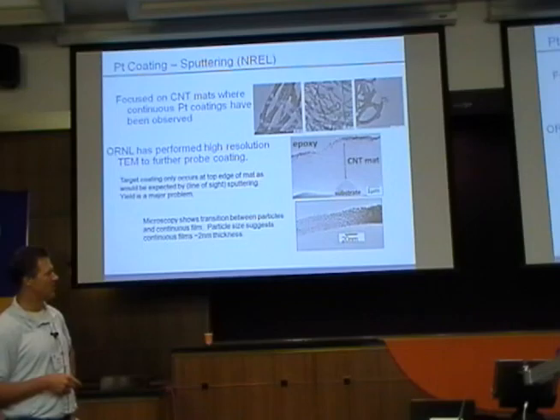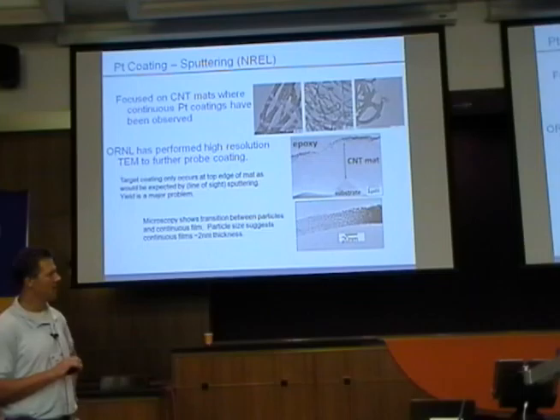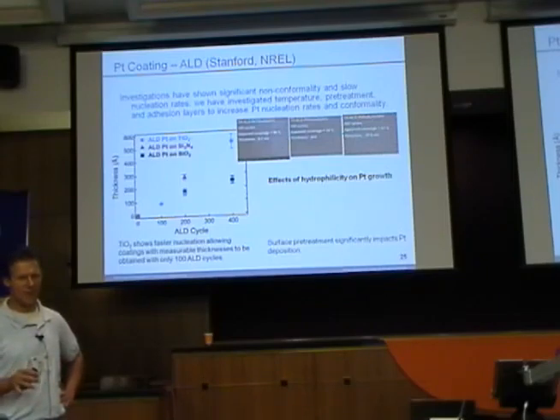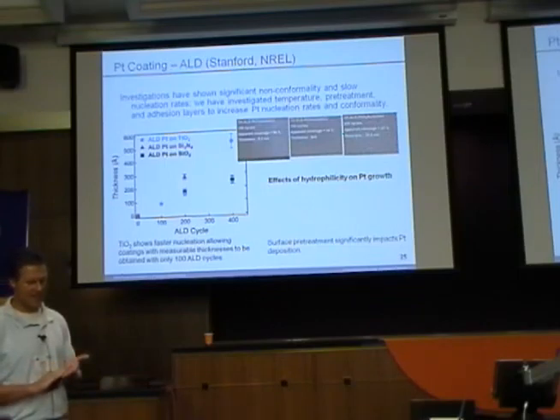However, based on what they have done and on some of the things that we've seen, it's the only approach that allows you to put these types of thin coatings down at the single nanometer level on things like carbon nanotubes. ALD is what we had hoped we could do with this. However, our best coatings so far have been in the 6 nanometer range as far as conformally coating. And to actually get to the mass activity targets we want, we have to get down to 1 or 2